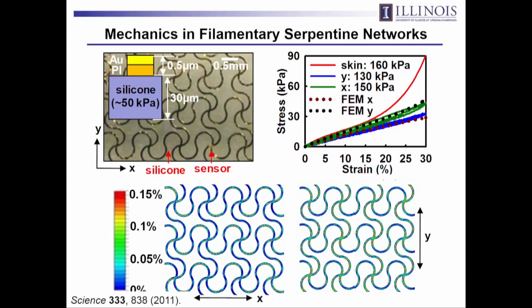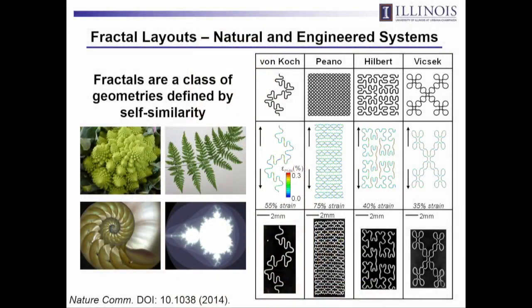So if you think about it from an electrical engineering standpoint, now you have to add on top of circuit design, mechanics design to get the full system function that you'd like to have. So this is sort of an ad hoc approach to make a more systematic design strategy. We found that the ideas of fractal mathematics turn out to be very, very helpful. So you can take these kind of fractal curves and then essentially tile any area, at any level of coverage, with these active filamentary serpentines in a very systematic way that allows you to do sort of top-down design of the mechanics. So we looked at lots of fundamental fractals such as von Koch curves and Peano curves, Hilbert, Vicsek. And these things are known, but nobody had looked at the mechanics before. So we've studied this in a quantitative way. We understand the level of stretchability and how it relates to the level of iteration in these different fractal geometries. And this turns out to be a very good way to do things.